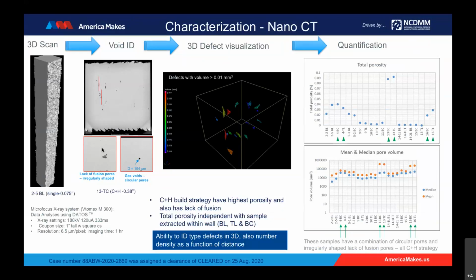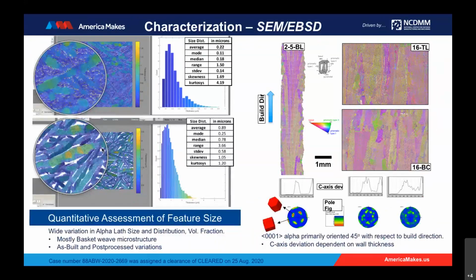The second part I want to point out is the quantification and the determination of the orientation of the lath structure here. As you can see on your left, there's a comparison of statistical distribution of the HCP alpha lath size, as well as the lath distribution for different heat treatments. So on the top left, you have the as-built plus stress relief sample, and on the bottom left, you have the fully heat treated sample. You can see that the average lath size has changed, but also the distribution of the lath has changed during the heat treatment, which is a great deal of information which we didn't have before. Similarly, on the right, the colorful maps that you observe are due to the crystallographic orientation of the alpha phases. So this clearly exhibits a 45-degree texture of large-scale alpha laths with respect to the build direction. So this was a significant finding because this will be impactful in some of the property data that Shrikar is going to share later on here.